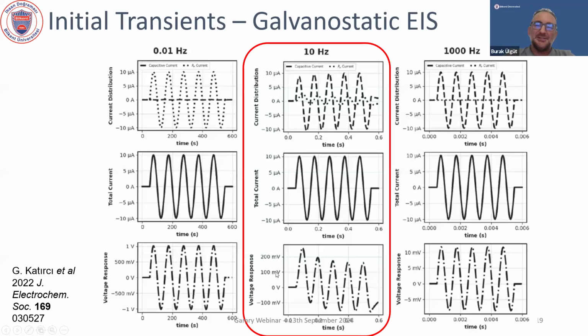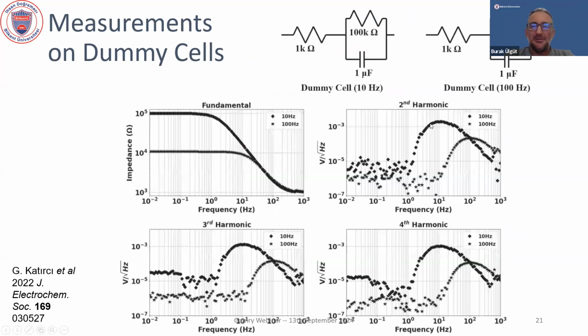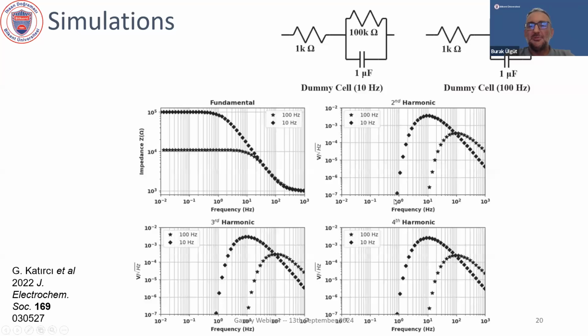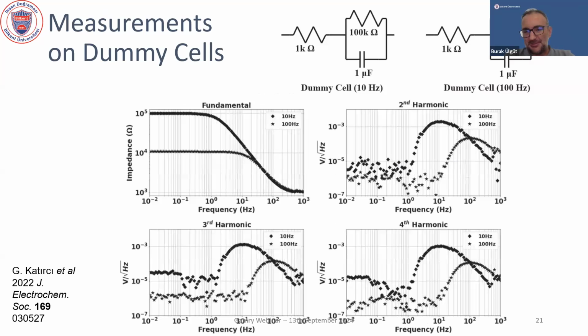So this initial transient, and this is the point I'm trying to make, even if you get rid of the first cycle, the second and the third and the fourth still have a transient response, which is exactly what we are seeing here. And what you're seeing at these low frequencies is just the instrument noise floor. This slide shows you that we can actually simulate this to the T. The only thing the simulation results are missing is the noise floor. If I added the noise floor to this, it would look exactly like the next slide, which is the measurement results.